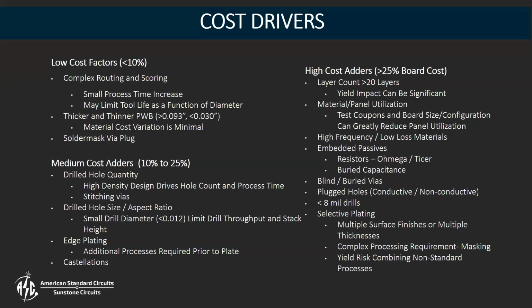Blind and buried vias with multiple lamination cycles are higher cost adders. Plugged holes with epoxy, conductive and non-conductive, have a lot of additional steps that go on with them. And then selective plating thicknesses, if you need multiple different surface finishes on the same panel, again requires multiple manufacturing sequences through the same type of sections. Obviously some of these need to happen to make your designs, but anytime you can limit or eliminate those from your design, if you're cost sensitive, the better the overall cost will be.